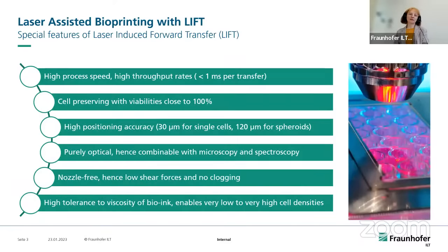What we do with the laser-assisted bioprinting with LIFT is that we use the very high process speed and the high throughput rates. We have less than 1 millisecond per transfer, and our cells live with up to 100% viability, and this is really good. We have high positioning accuracy, which depends on the dimension of the particle we print. A single cell with a diameter of approximately 20 to 30 micron has an accuracy of 30 micron. If we have larger particles, the precision may change.